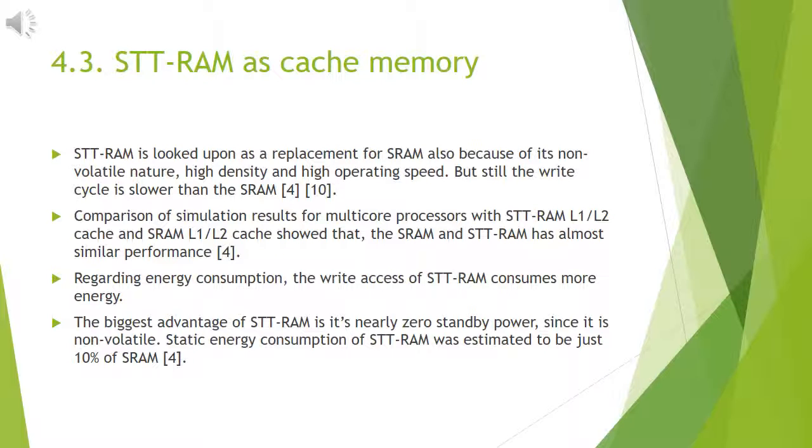Let's look into using STT-RAM as cache memory. Simulation results show that the performance of STT-RAM is almost the same as SRAM. Write access consumes more energy, but the static energy consumption is just 10% that of SRAM.